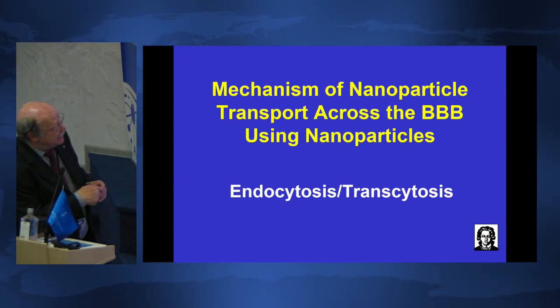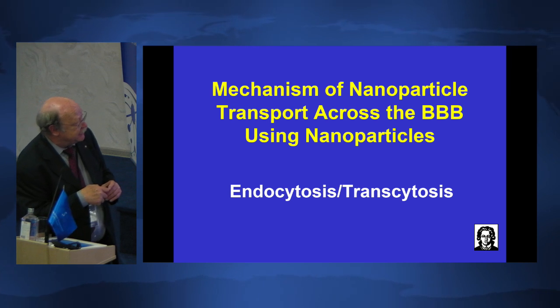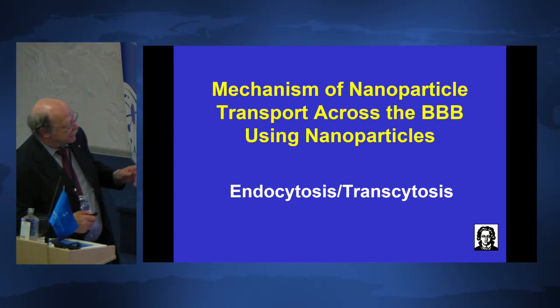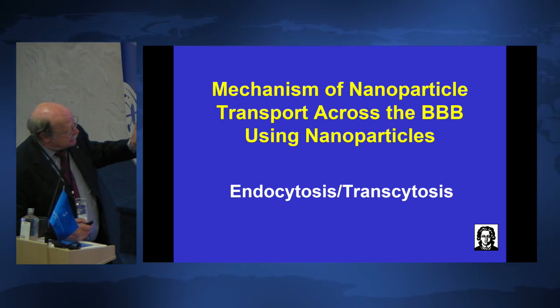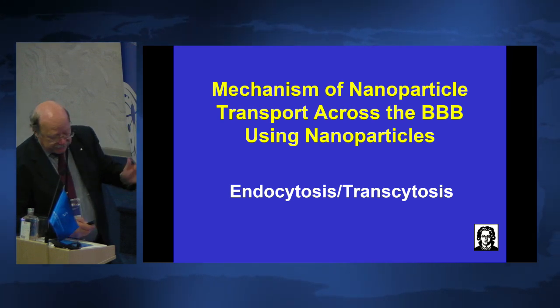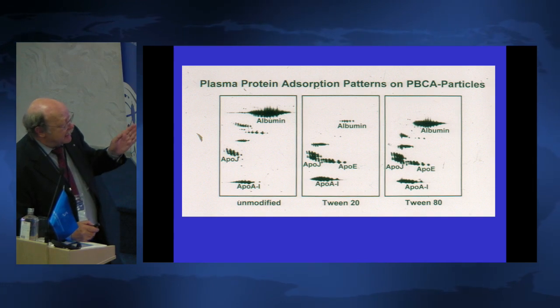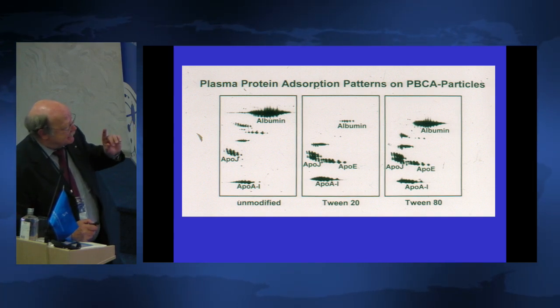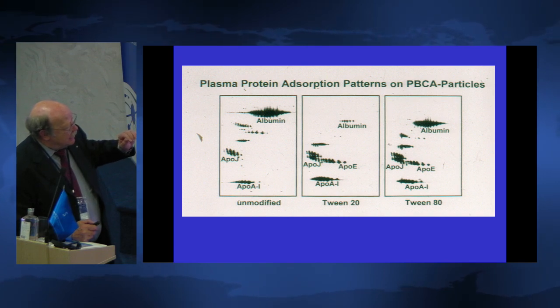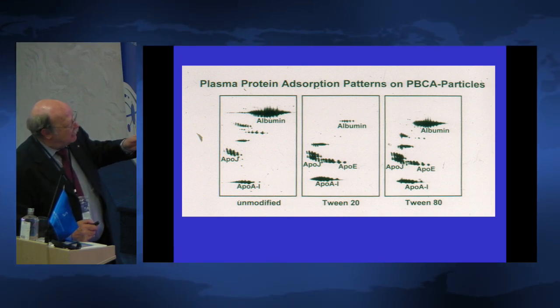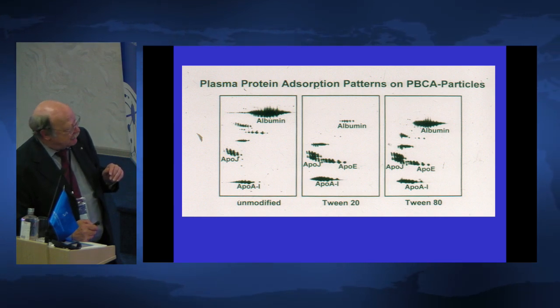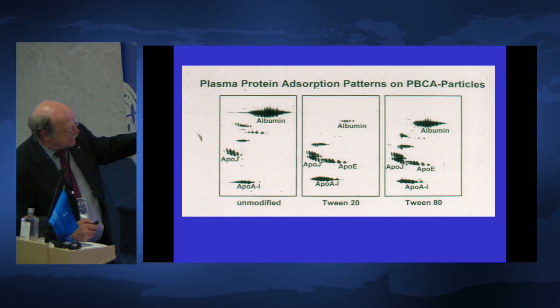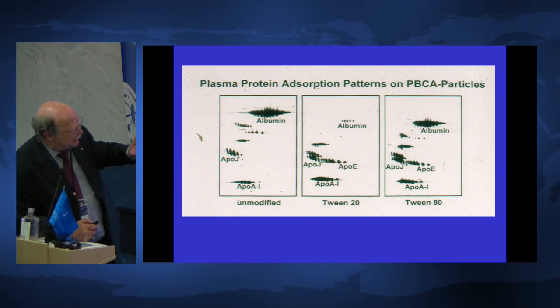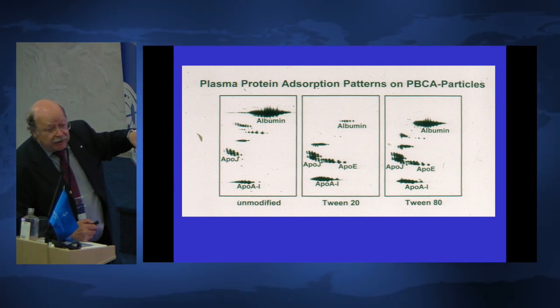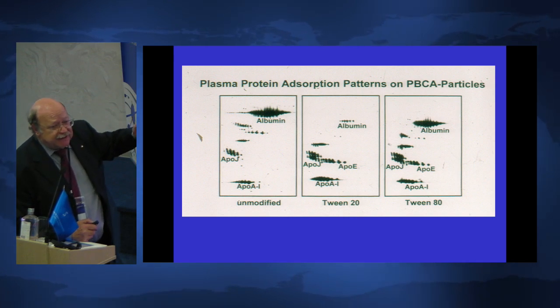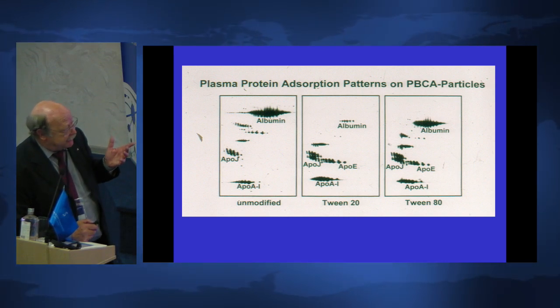Well, what is the mechanism of nanoparticle transport across the blood-brain barrier with the nanoparticles? To make a long story short, it's endocytosis followed by transcytosis. We, together with Rainer Müller in Berlin, realized at that time that when we used the nanoparticles in vitro and looked at the plasma protein adsorption pattern, we found that polysorbate 80, and also polysorbate 20, but not as efficient, were able to bind apolipoprotein E from the blood on the surface of the nanoparticles.